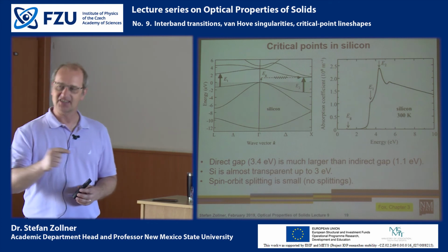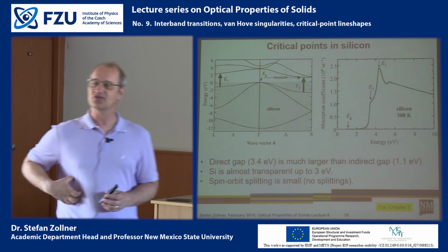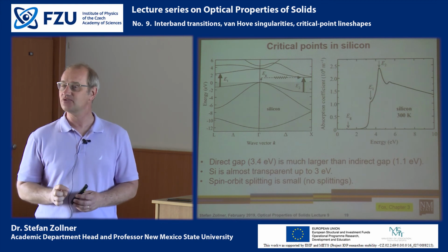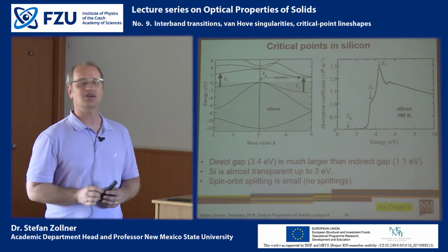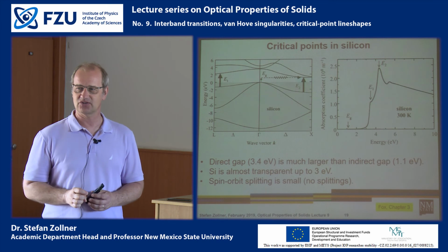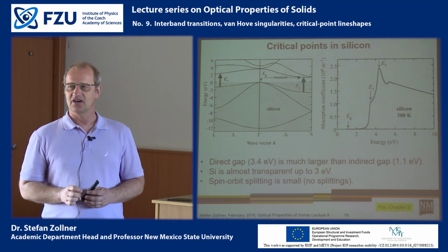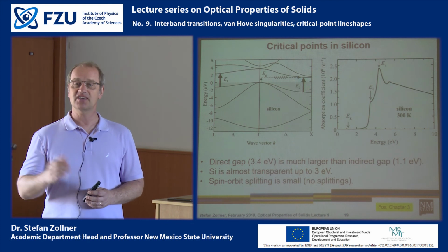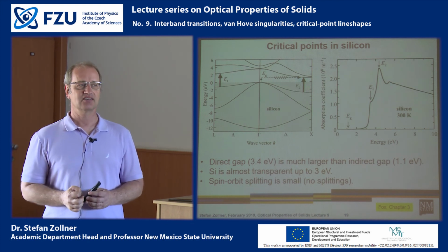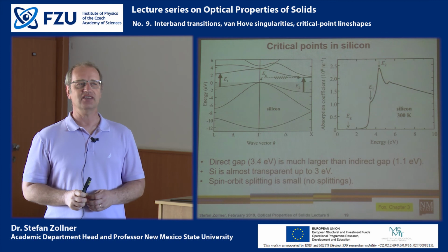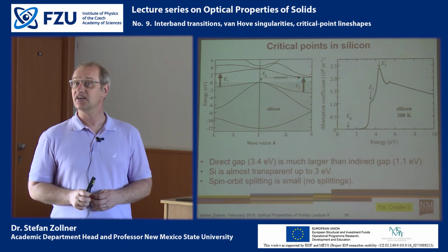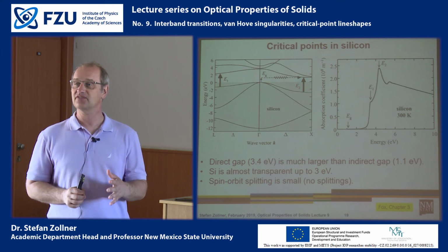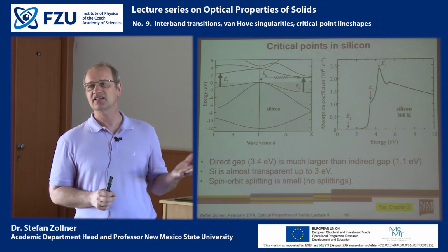So they are not very good polarizers, but you can do ellipsometry up to 25 electron volts using synchrotron light sources. Beyond that, I'm not aware of any ellipsometry setups that go beyond 25 electron volts. The 25 electron volt instrument is in Berlin.